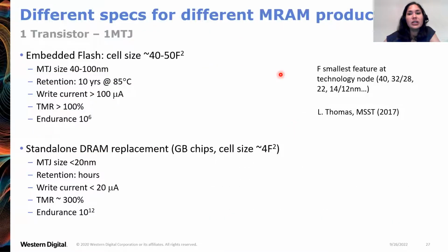And the different products will require different specifications, different values for these specs. So you can tailor the MRAM stack for these various applications. So for example, here, the MRAM stack that is used for embedded flash replacement, this uses magnetic tunnel junctions that are 40 nanometers in diameter and above. The retention spec is typically 10 years at an elevated operating temperature, write currents above 100 microamps, TMR above 100%, and endurance about 1 million cycles.